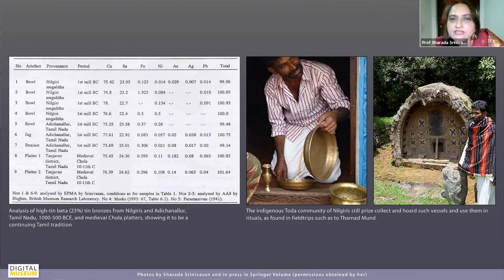This is just to show some of the analyses of some of these vessels, because I've been just talking about this 23% composition. But here you can see some of the vessels from the Nilgiris and Adichanallur. The tin content is quite a narrow band of about 22 to 23%. And there's no lead in it or any other alloying elements. And this tradition also continued in South India for a long time. Of course, we've seen the continuing tradition, but I've also looked at some Chola vessels which have a similar composition, aiming for this high-tin bronze, 23-24% tin bronze composition.